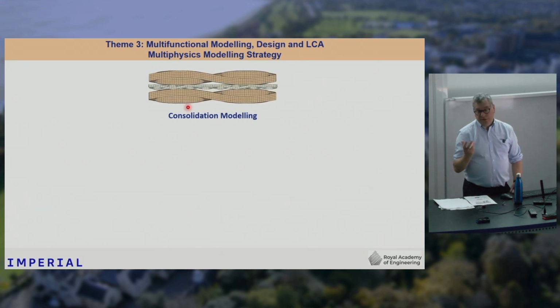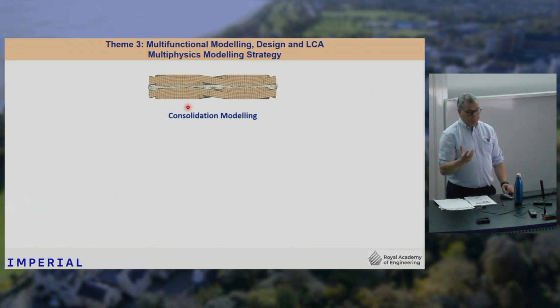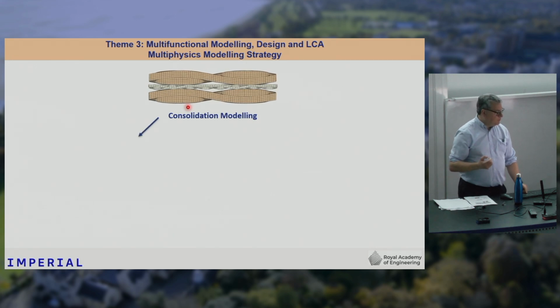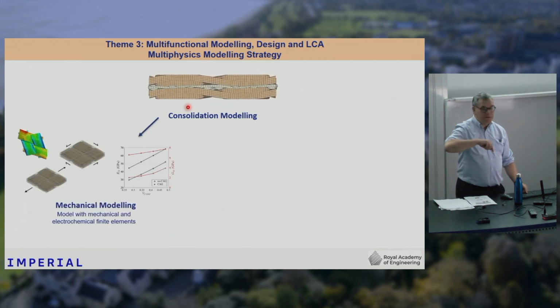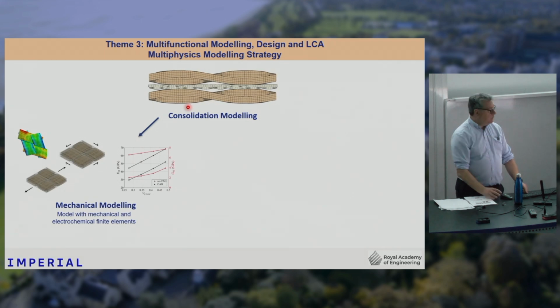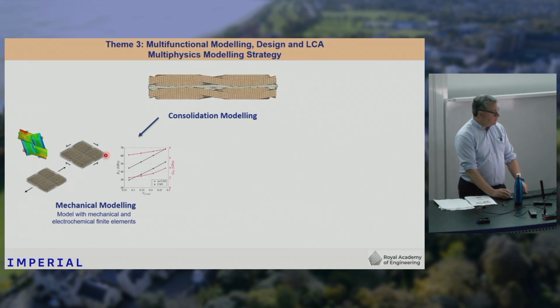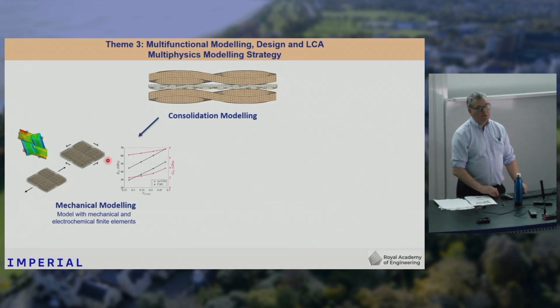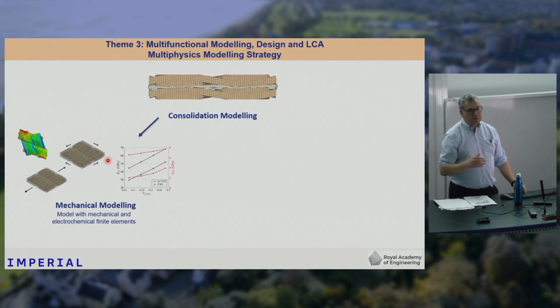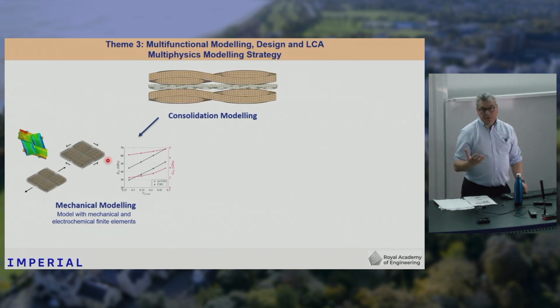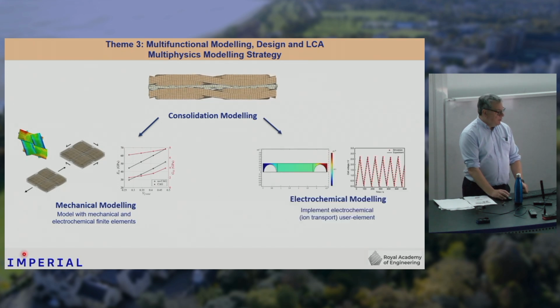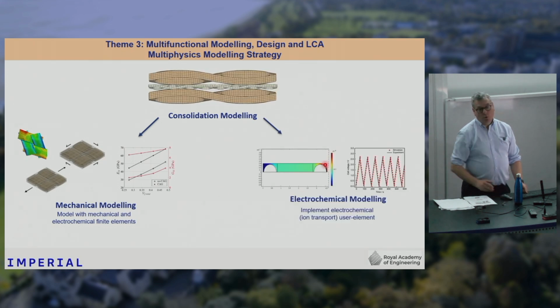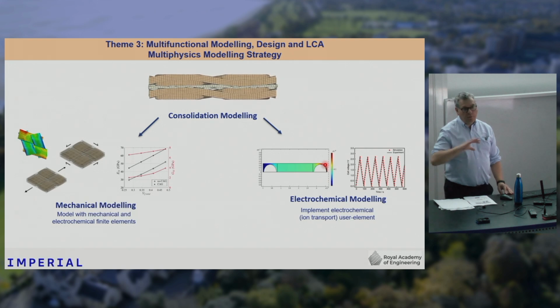So we're able to predict the microstructure of our material during the processing. And then we could implant that into an Abaqus model of the mechanical properties, which is shown here, where we can vary things like volume fraction of the fibers and matrices to give us a prediction of elastic performance. And we also can take that model as an electrochemical model. Okay, so that's kind of where we're going with things.